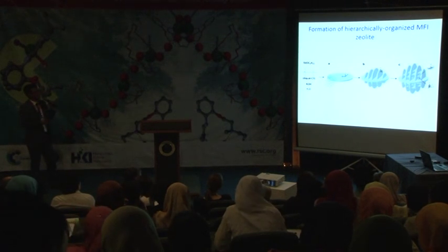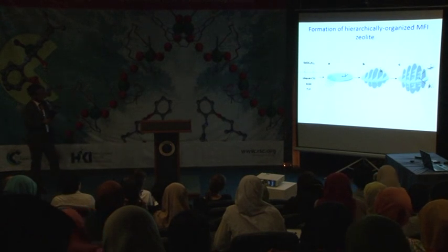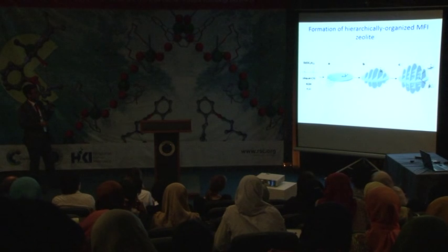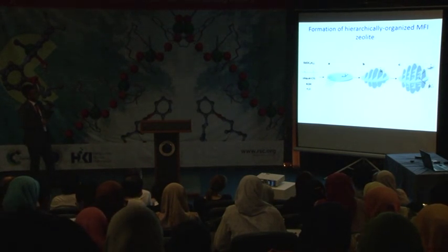And we also tried to understand the mechanisms. It works from nanoparticle formation, and then they make thin plates, and then suddenly the 90-degree rotational intergrowth occurs. It is also influenced by the temperatures applied during the synthesis of zeolite.